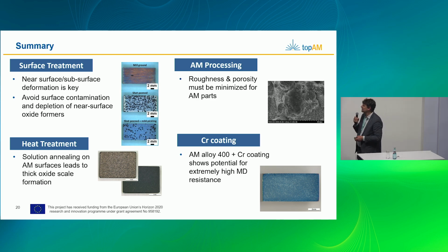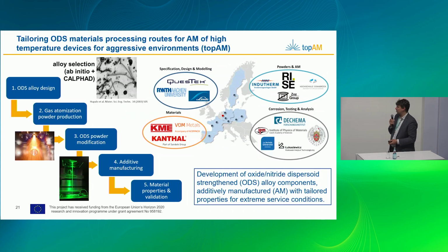As I said, surface treatment is key. The heat treatment as well, because you might form internal oxides. You can change your alloys not only in the way that you want to. We need to basically work on this roughness and porosity when it comes to an oxidation point of view, because just the large surface is basically prone for corrosion and attack. And this combination of a post-heat treatment, for example, with a coating process, might be a very good way and path forward.